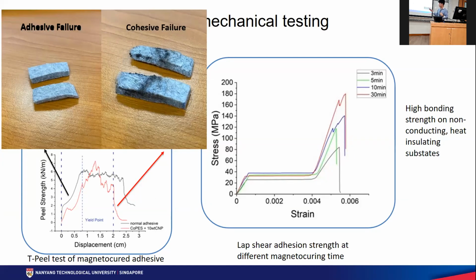From the peel test, we're testing the magneto-cured adhesive against a normal commercial adhesive. And what we find is very interesting. For the normal commercial adhesive, we find a more stable peel strength, which is the black line, but with adhesive failure, meaning all the adhesive sticks to one side of the substrate, whereas on the other substrate, no adhesive was found. However, when we look at the magneto-cured composite, we saw that both of the failed substrates have adhesive, which is cohesive failure, and we also obtain a higher maximum peel strength.